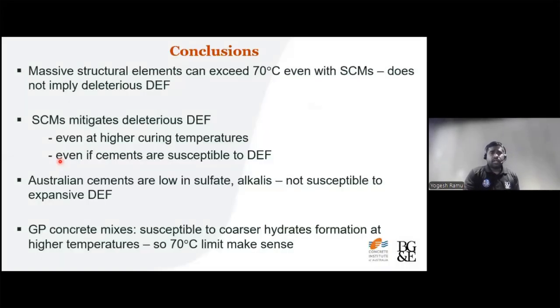So to conclude, massive concrete structural elements can easily go beyond 70 degrees Celsius even with SCMs. The advantage with SCMs is that they can mitigate DEF even if the temperature goes beyond 70 degrees Celsius, and also can help in pore refinement as well. And also, SCMs can help even if the cement by accident has much higher sulfates and alkalis in it. If we are getting some cements from abroad and accidentally it has more sulfates in it, even in that situation,